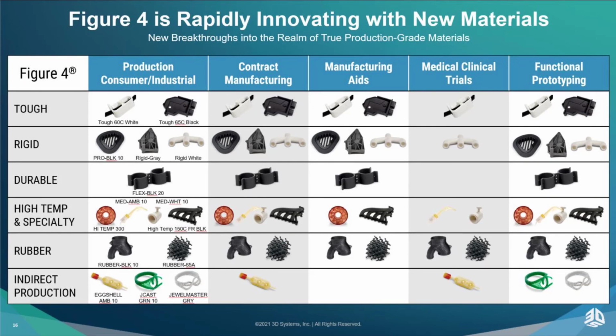But the other part is, from a production perspective, one of the things we did is we make sure in the data sheet to have isotropic data, which is very important when you're looking at organic parts, what's the isotropy of the mechanical properties? And that will play a role into your part and material selection. And in addition to that, there is an automotive fluid compatibility from US CAR 2, and then there's an ASTM D543 spec for chemical compatibility for industrial detergents and cleaners. And so you'll see the same mechanical properties tested in the long-term stability and those other tests so that you can look and comparatively see to help dial in what material you need for an application.